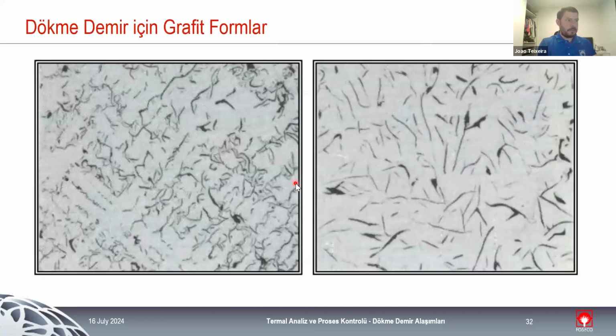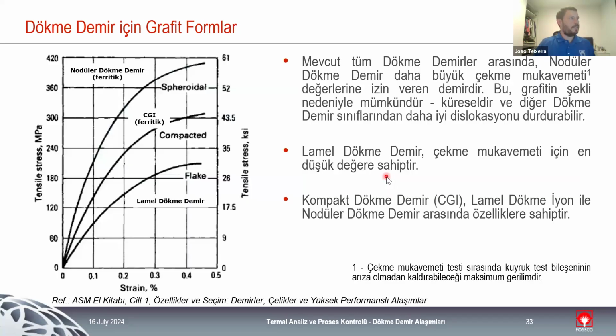This is just an example of the change between the different types of gray iron that we can have, and you can see that on the right side we have more graphite type A, so we probably have better mechanical properties and overall quality of the cast. Here, it's just for us to see the difference in tensile strength between gray, compact, and nodular. So we have higher tensile strength with nodular. It's more difficult to produce, but we have more mechanical resistance in this type of iron.